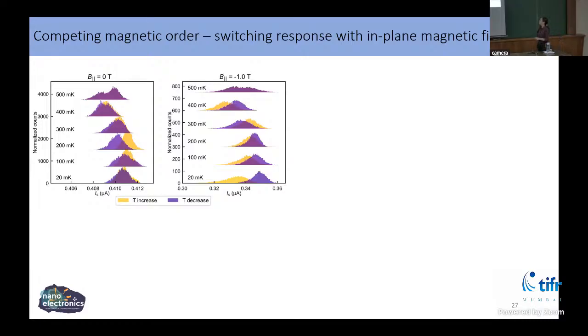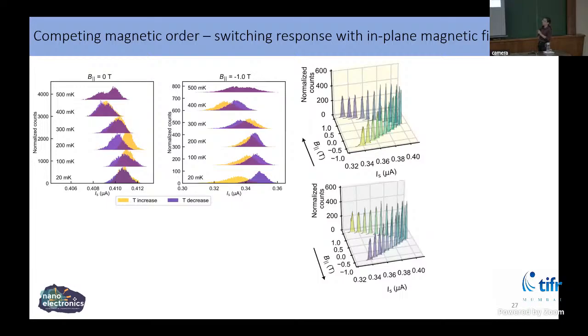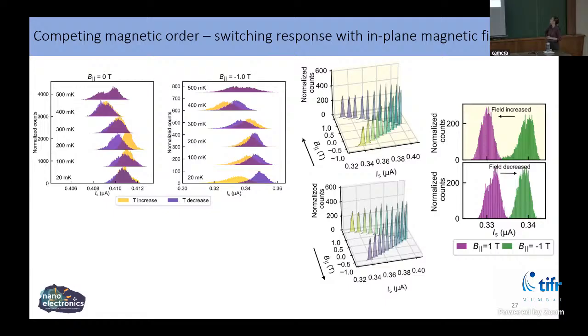We also studied these histograms as a function of in-plane magnetic field at a stable base temperature of 20 millikelvin. Basically, we cycled the magnetic field going from -1 to 1 Tesla and then back from 1 to -1 Tesla. What we always found to be true is that the switching histogram for 1 Tesla, which is this purple one, always had a mean current smaller than the one for -1 Tesla. So this tells you that the system is preferential to a particular direction of the magnetic field, in the sense that 1 Tesla and -1 Tesla are not equivalent to the system.